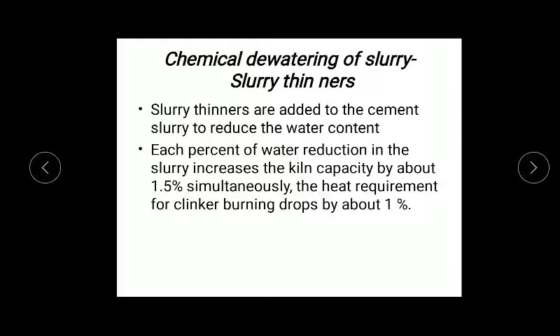Chemical dewatering of slurry by addition of slurry thinner, some amount of alkalis are added into the slurry. So we'll see what those alkalis are. Slurry thinners are added to the cement slurry to reduce the water content. Each percent of water reduction in the slurry increases kiln capacity by about 1.5%. Each percent means if you are removing 1% of water from the slurry, then you are improving the kiln capacity by 1.5%. Simultaneously, the heat requirement for clinker burning drops by 1%.